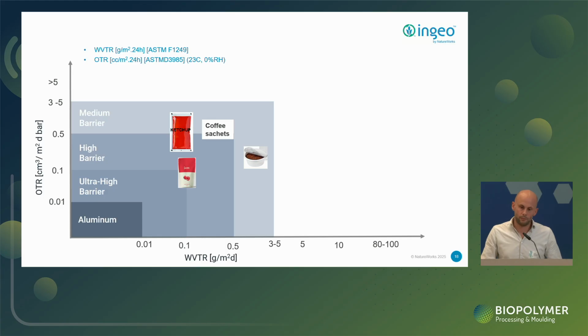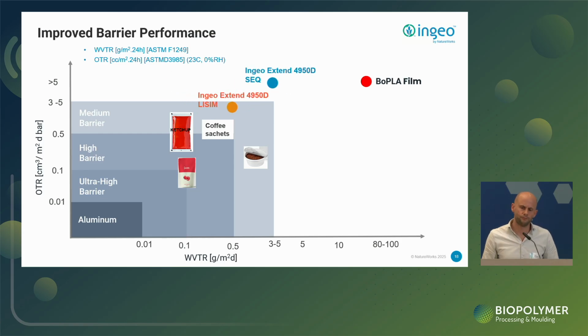And for the applications that initially have been mentioned, barrier properties are a must. They are essential. And unfortunately, most of the biopolymers have a quite high moisture transmission rate. You see it here on the x-axis. This is a commonly used BOPLA film that's quite outside the requirements that you have for such applications. And by applying certain coatings, you see that the simultaneously stretched film has even better performance. The water vapor transmission rate has been between medium and high barrier, so an excellent result already.